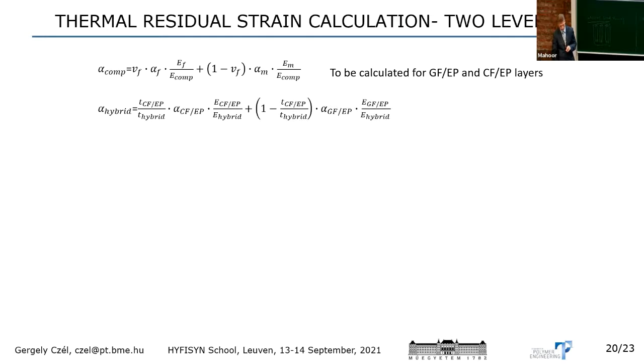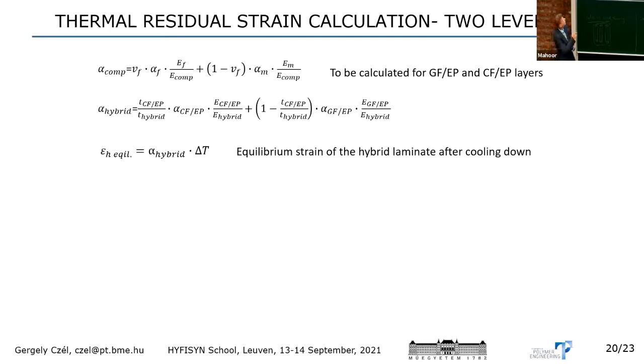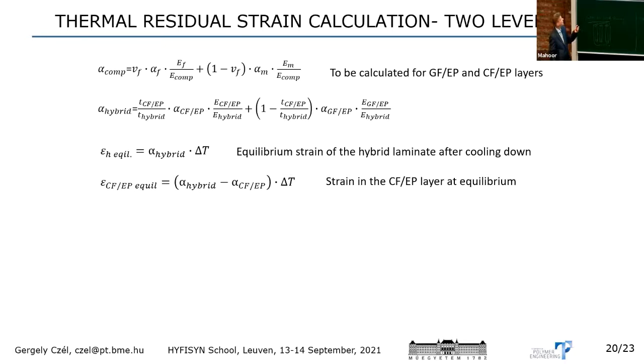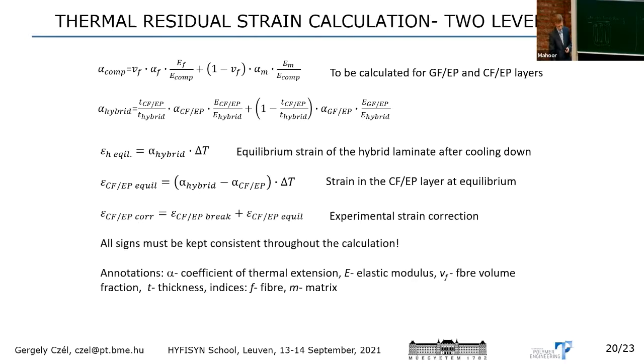And in this case, we also have the, you don't see my mouse, sorry. So we still have the stiffness term, and then the volume fraction is replaced by the thicknesses. But we can do this quite quickly and come up with a thermal expansion coefficient for the hybrid, and then we can straight away work out the equilibrium strain due to cooling down from 130 to, I don't know, room temperature. And then we can also correct our results. I just wanted to demonstrate that this is not rocket science, so anyone can do it with quite simple considerations.